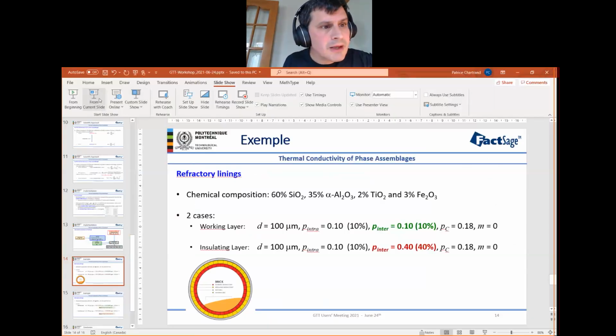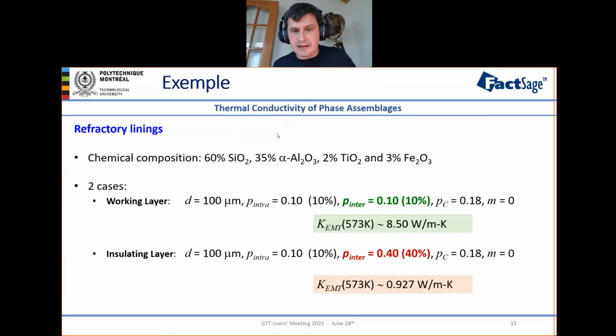I go back to my presentation. All right. And as you can see, there is a very big difference in the thermal conductivity with the same phase assemblage except for the porosity, going from 10 to 40%.